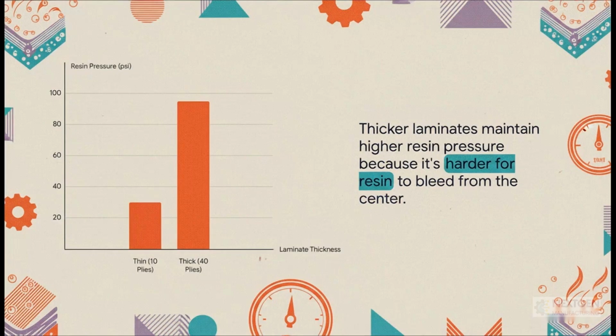You know, the thickness of the part itself plays a massive role too. This chart shows it perfectly. In a thin part, say 10 layers, the resin can escape pretty easily, and you see a big drop in pressure. But in a thick 40-layer part, it's way harder for the resin in the middle to find a way out, so that crucial hydrostatic pressure stays high, almost perfectly matching the pressure in the autoclave.